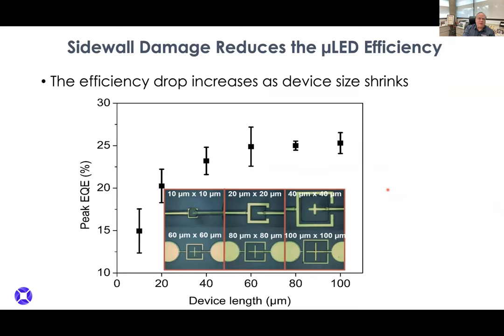So what was the big problem, and what continues to be a big problem, when you reduce the size of the LED from something that's really big to very small, is you can see here, this is what's called EQE, or external quantum efficiency. This exactly measures how many photons of light you get out for every electron you put in. So 25% means that for every electron, there's only a 25% probability that a photon will come out. And so you can see as we go to smaller sizes, the efficiency drops pretty quick. So that was a big problem.